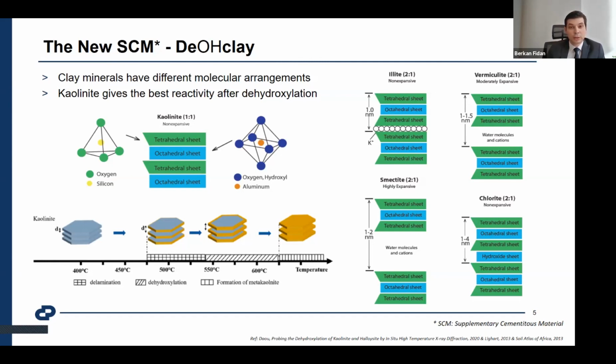Its reactivity is well known, but generally it's produced with high purity for different mineral processing industries. It's only partially used in the cement industry because of the high quality kaolinite required to produce that material. But in that part, low quality clays with 35–40% kaolinite content can be used in the cement industry. Its decomposition happens like this: it starts near 500 degrees, the delamination happens, and then it turns to metakaolinite as it reaches 650–700 degrees.